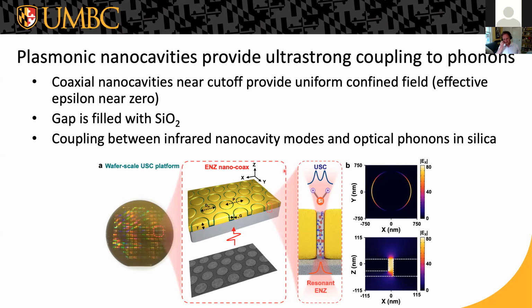So towards the goal of really reducing the volume involved in ultra-strong coupling, the work with Sung-Hyun Oh at the University of Minnesota developed a method for fabricating wafer scale arrays of really nanometer scale coaxial plasmonic cavities. These are basically films of gold that have small rings cut through them, filled up with a dielectric material, in this case silicon dioxide. So these rings are acting like coaxial waveguides with nanometer scale, few nanometer gaps between the metal walls of that waveguide.